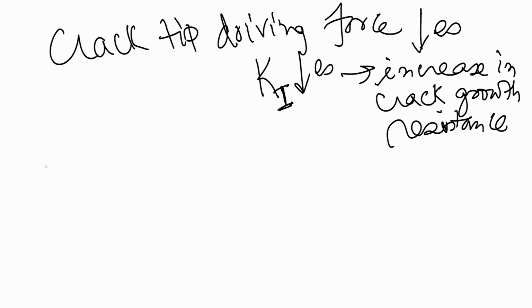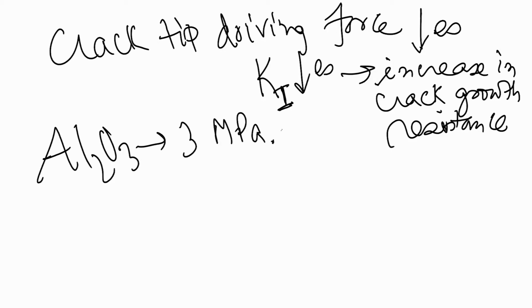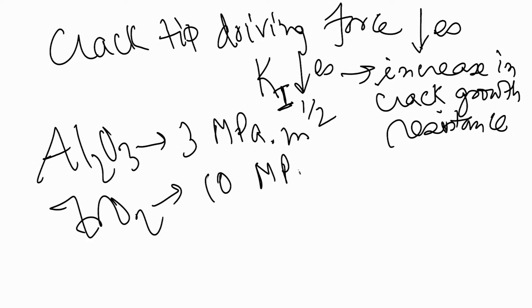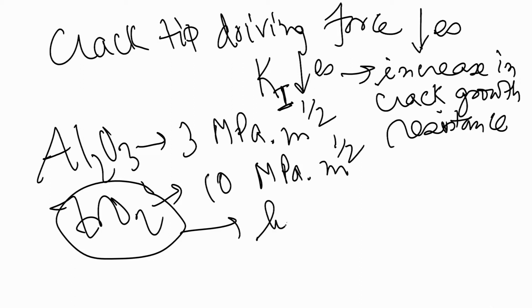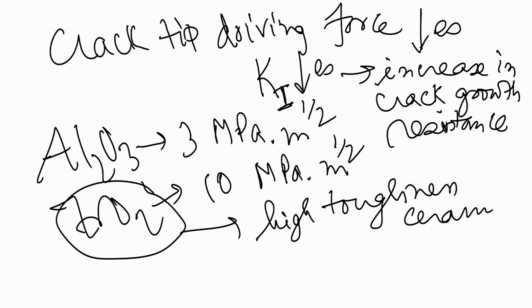Okay. So, for example, alumina, their fracture toughness is around 3 MPa square root meter. For zirconia their fracture toughness is around 10 MPa square root meter. So, that is why zirconia is one of the materials which is considered as a high toughness ceramic. Okay. So, toughness is essentially a measure of the crack growth resistance. Typically ceramics are known for their inherent brittleness, and if fracture toughness is increased, then the application of the ceramics also would widen.